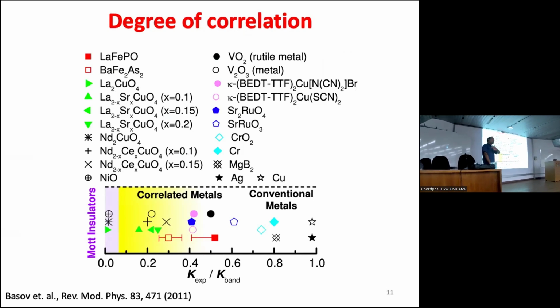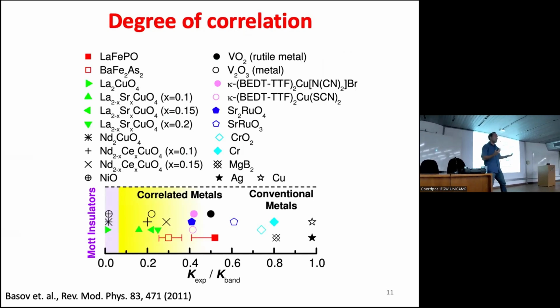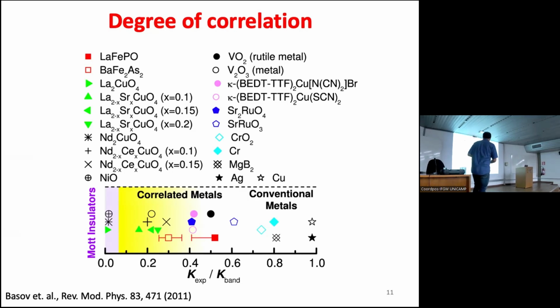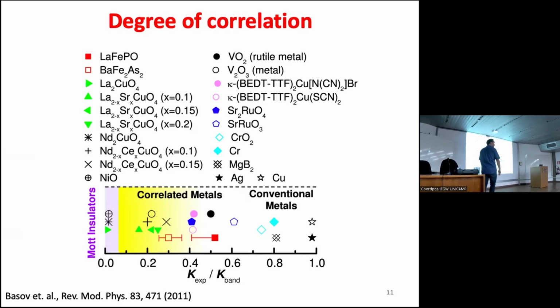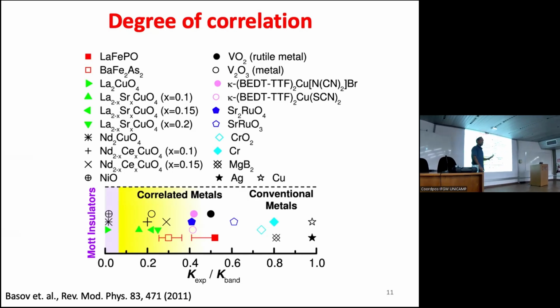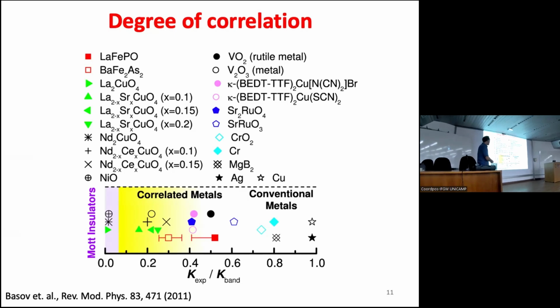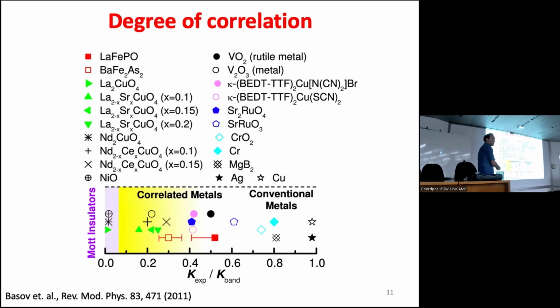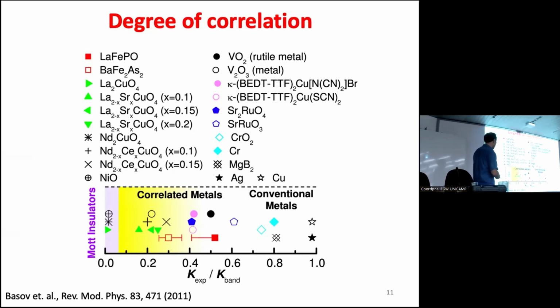DFT, not including any kind of electron-electron correlations, and then you measure the kinetic energy with some optical type of experiment. The ratio between these two, how different they are, is basically how correlated they are supposed to be. This is where you get the most correlated materials. Here's where they don't. Basically there's a match between the two. So vanadium oxide, V₂O₃, is over here, so it's somehow correlated.